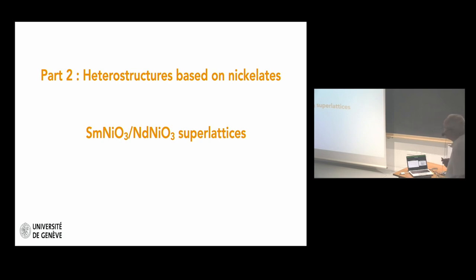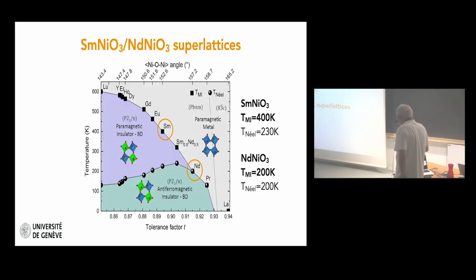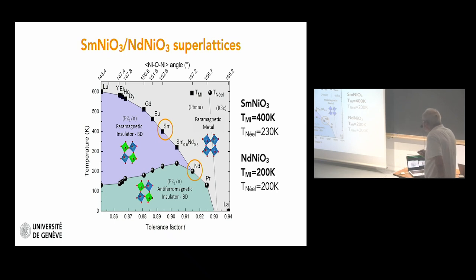Okay, so let me move now to this part where we have realized different types of superlattices with nickelates, and you will see how the things which have been introduced before are useful. The first thing we did was to realize heterostructures made with two different nickelates, and we chose samarium nickelate and neodymium nickelate. These two nickelates have two different metal to insulator transition temperatures, but also different distortions. Samarium nickelate is more distorted than neodymium nickelate.